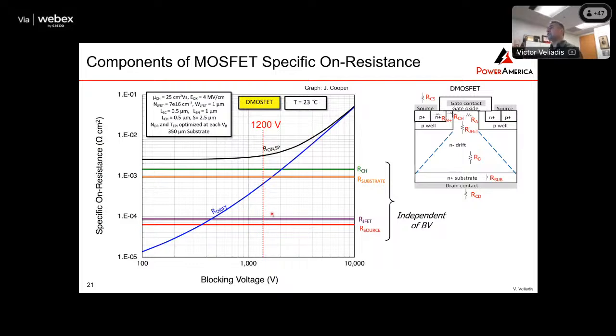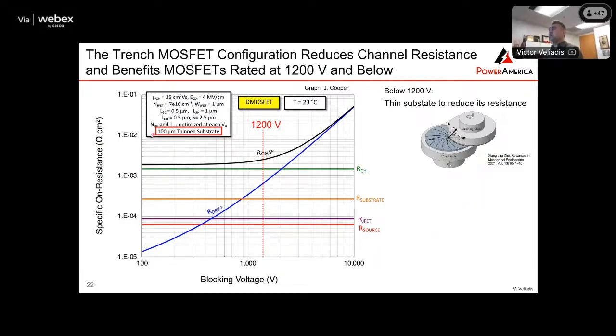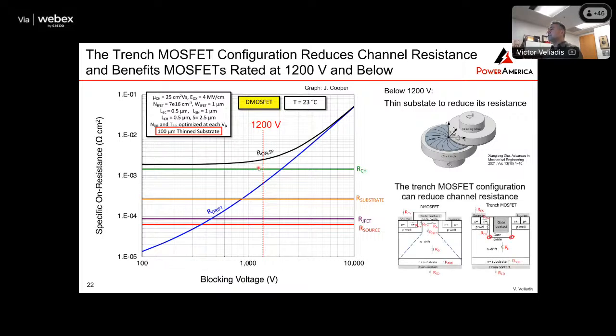So for the 1200 volt devices that are very important, we have the substrate resistance that's very high and the channel. If you look at this graph right here, it shows a substrate of 350 microns, which is the thickness of the substrate as you buy it from the market. But then you can thin the substrate to 100 micron. Now you see how the substrate resistance has dropped significantly. So in order to reduce the substrate resistance, you thin the substrate, and we have the channel resistance, and the way to reduce, of course, the channel resistance, as I mentioned before, is to go into a trench MOSFET, which in theory can lower the channel resistance, although because of the trade-off of the electric field here and the tricks you need to do to take care of that, you know, it's not a clear win.